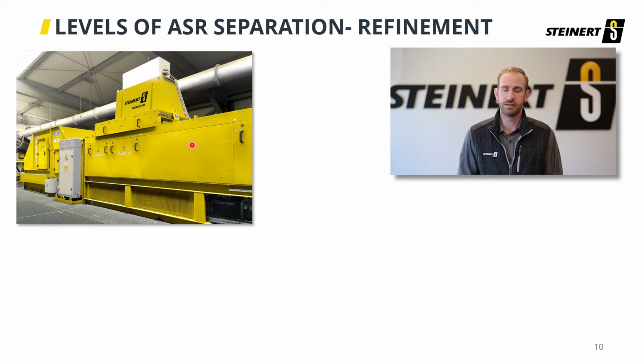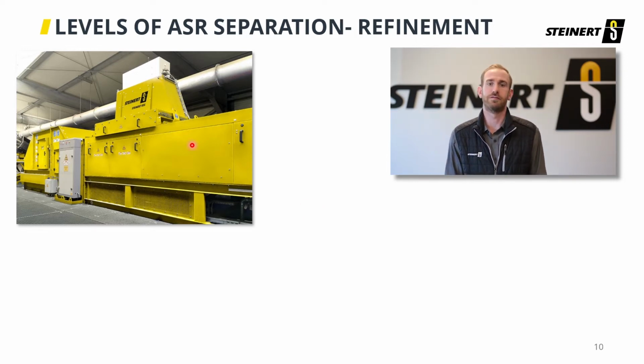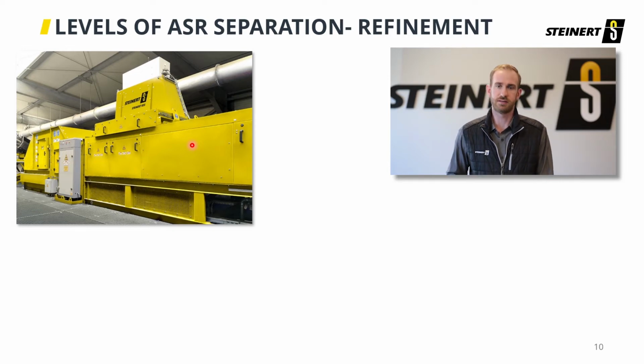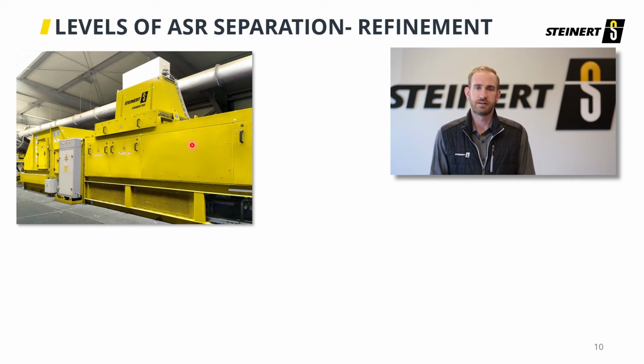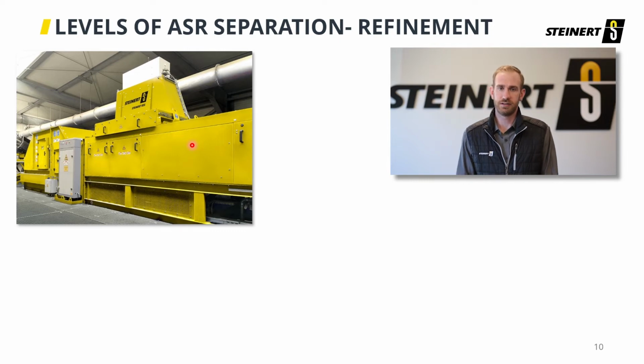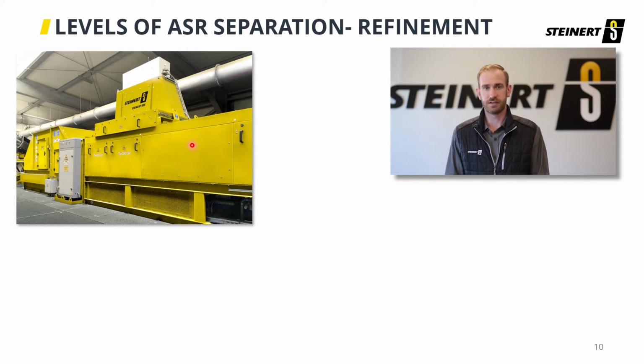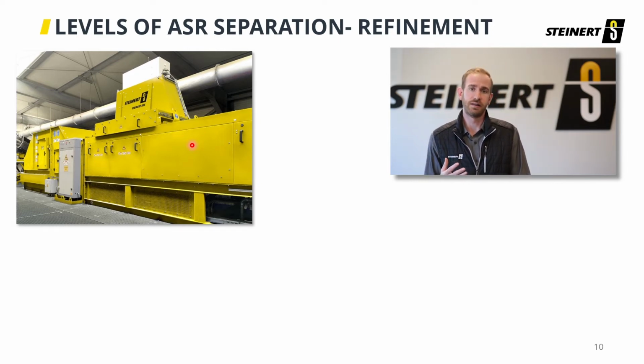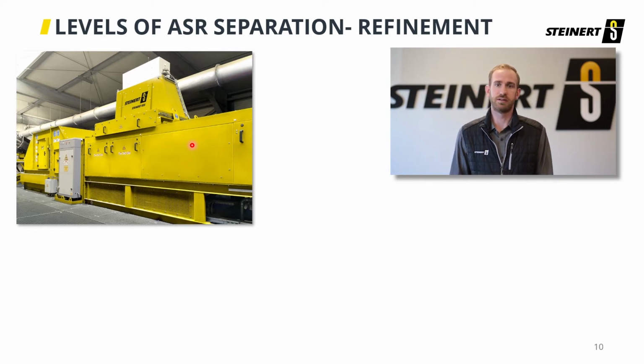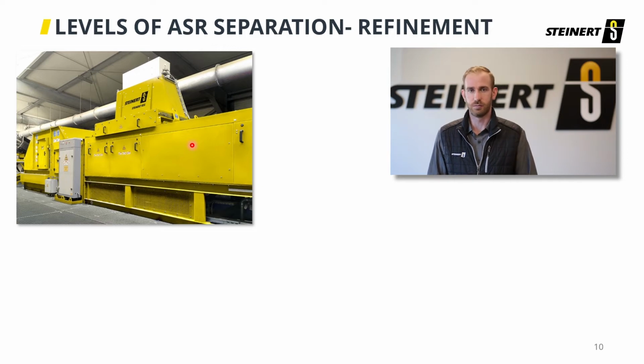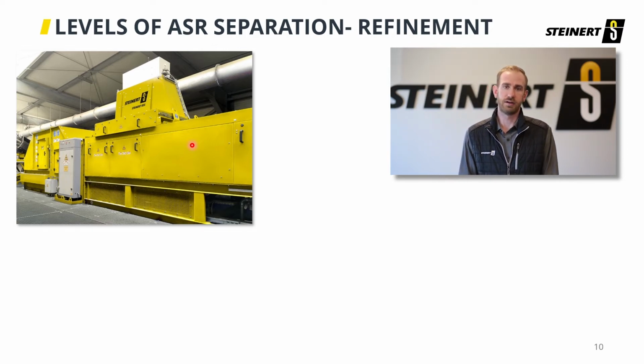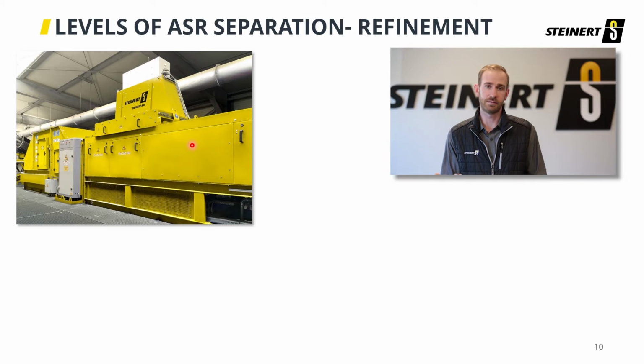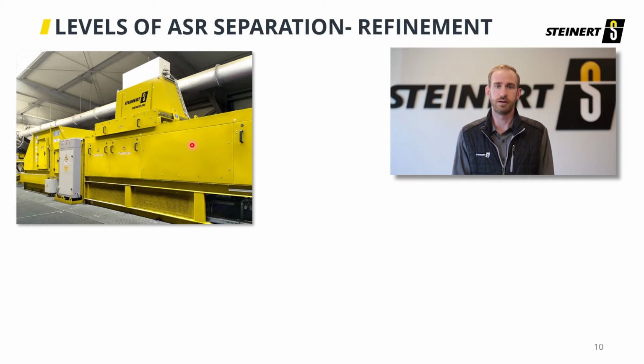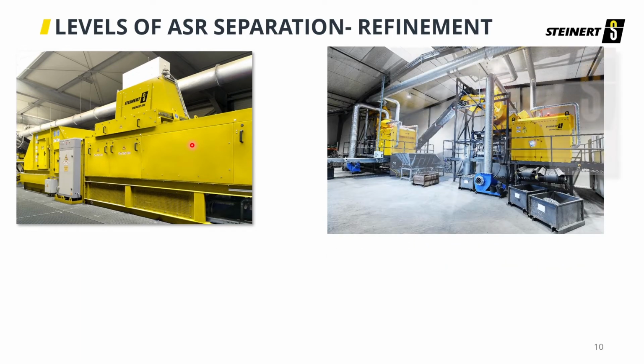For KSS XRT, this is really your first refinement step. The KSS XRT is going to lead the way. X-ray transmissive is a through technology, meaning that it's not just surface detection, it's actually sending energy through the piece so that we're able to detect high density spots in the piece. And that allows us to more accurately sort and classify pieces that may have some of those inclusions that we mentioned earlier.